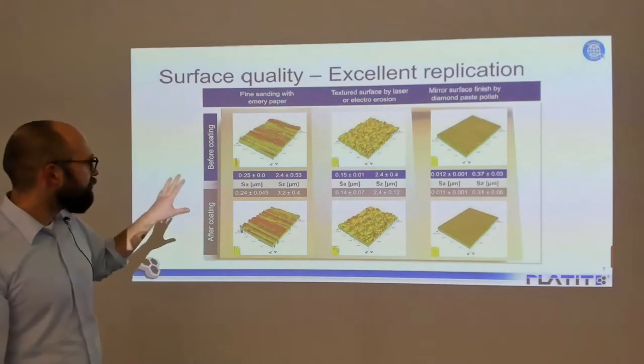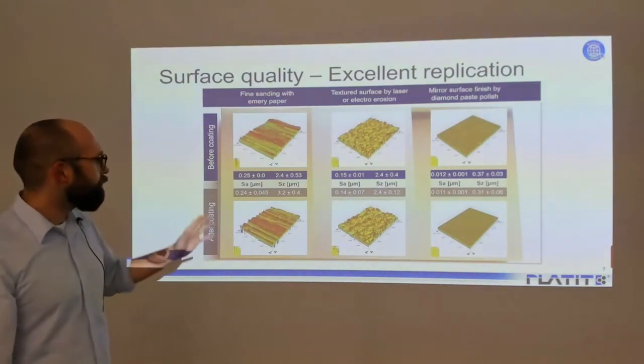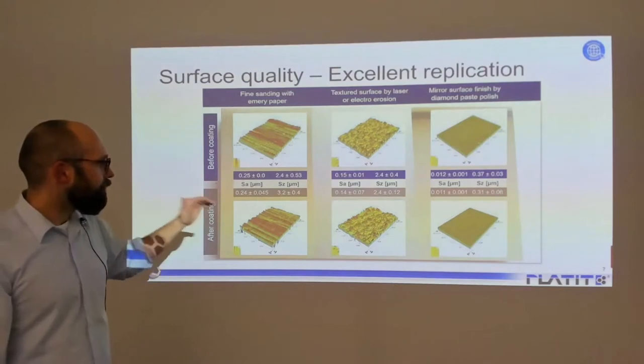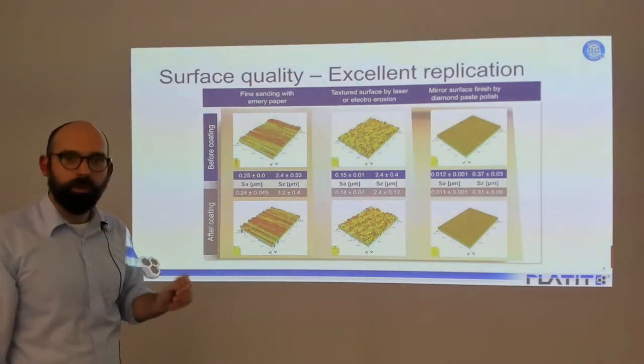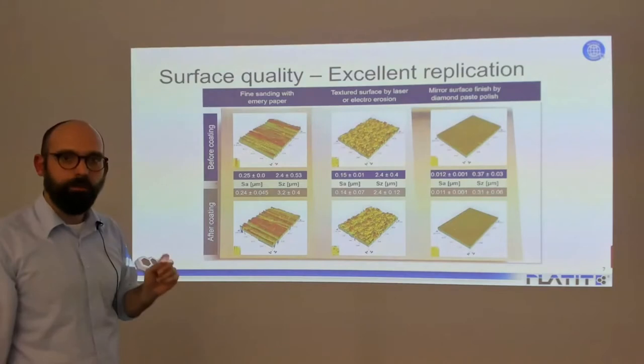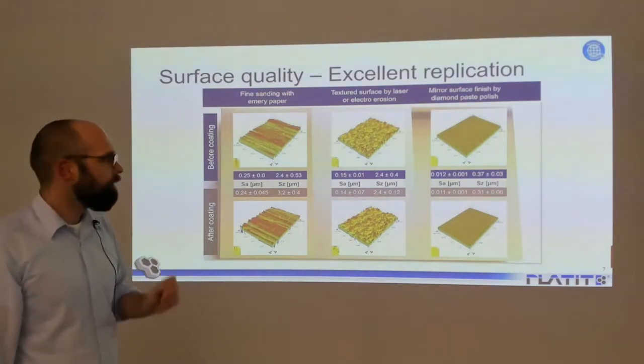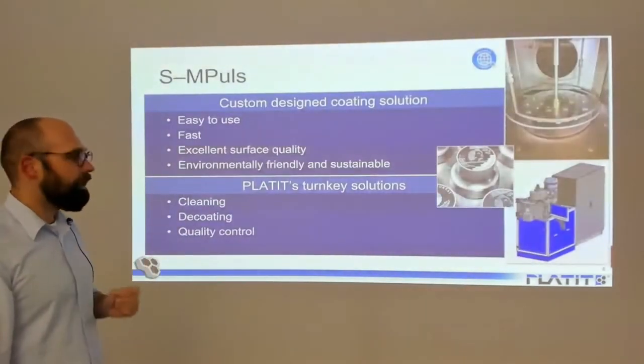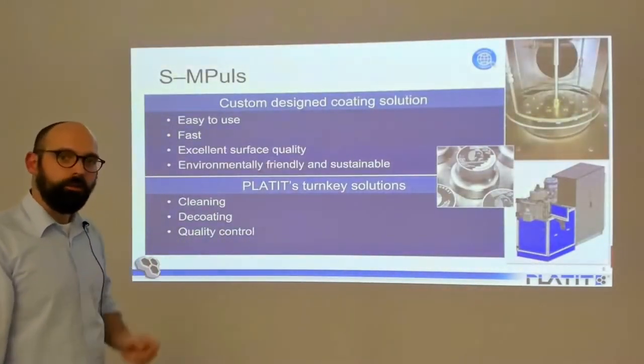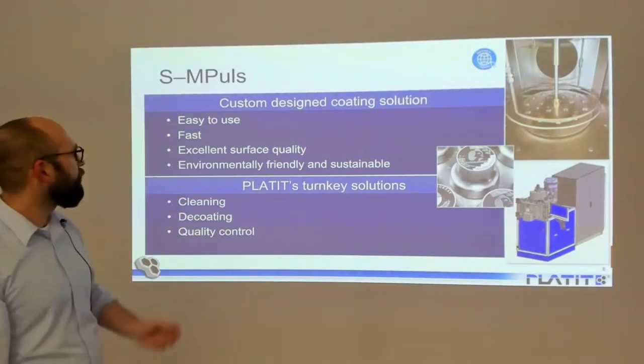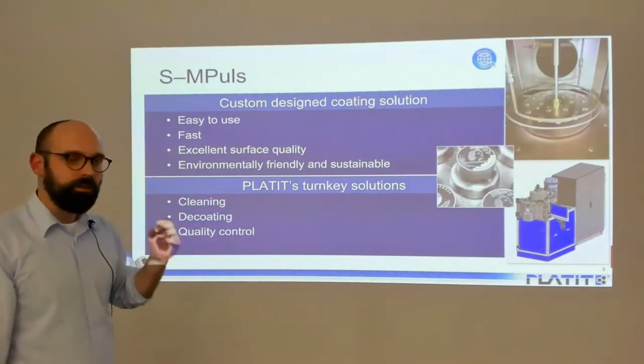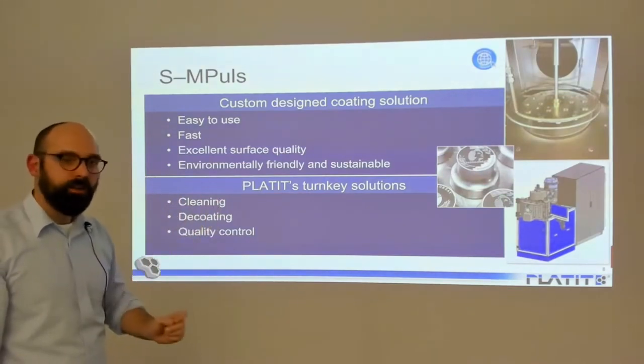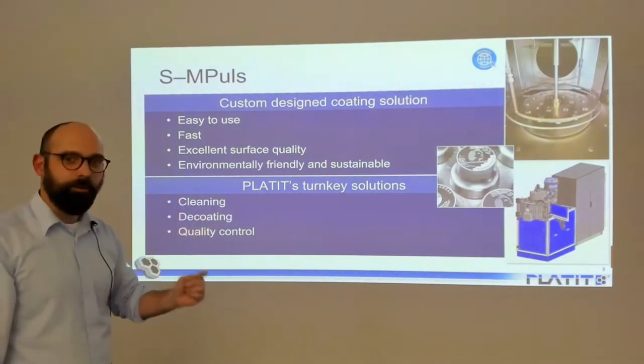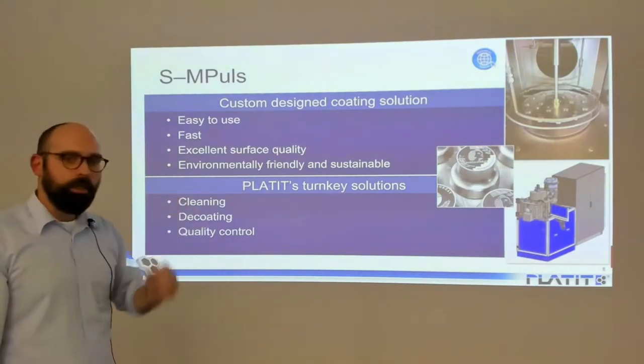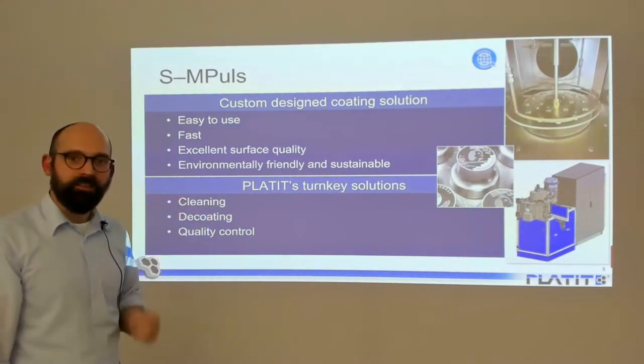And what you can see here is that you have literally no difference from before the coating to after coating, meaning that we form the perfect copy of your surface without disturbing it, without harming it, without any distortion. And with this, I'm already at the end of my presentation. I introduced to you the PLATIT S-MPuls, our new custom designed coating solution for coin stamps, which is easy to use, fast, provides really excellent surface quality, and the PVD coatings are environmentally friendly and sustainable.